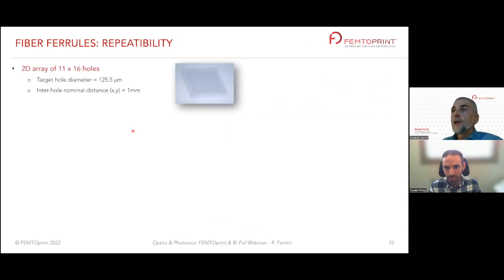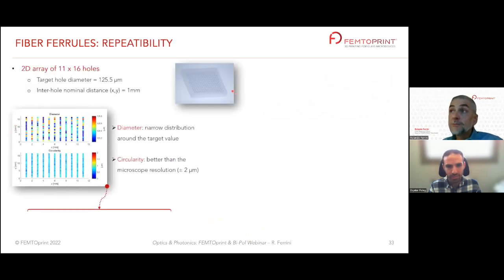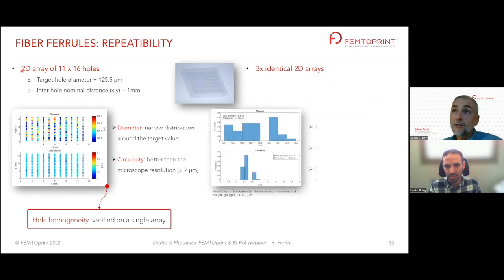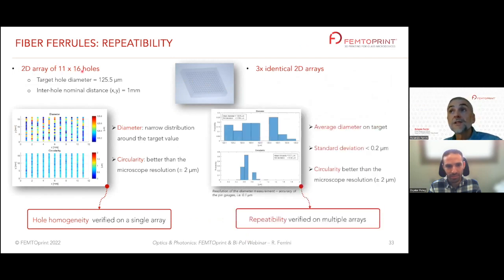And again, we have also checked the repeatability of the control on diameter on an array of, for example, 11 times 16 holes. We have a very nice narrow distribution of the diameter around the target value, and the circularity is better than what can be measured with an optical microscope. The resolution is in the order of microns, so we are better than 1 micron. We repeated it also on several arrays, and the average diameter is on target, the standard deviation is better than 0.2 microns, and the circularity, again, is better than the resolution of the microscope.